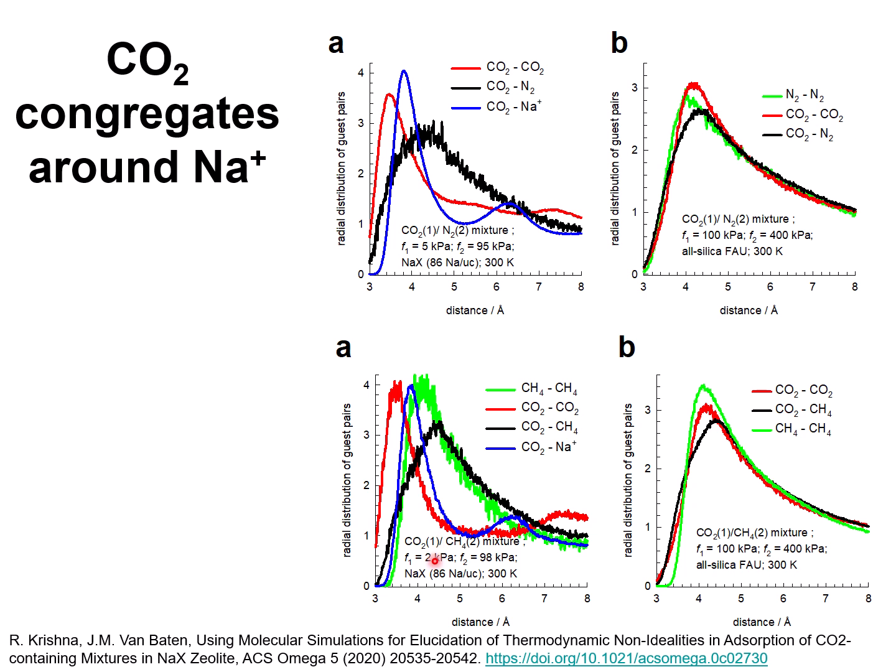distances in the mixture. This CO2 is much closer than CO2 methane, and the CO2 methane distance is larger than the distance between CO2 and the extra framework sodium cation. In other words, methane suffers less severe competition due to congregation of CO2 around the sodium cation.